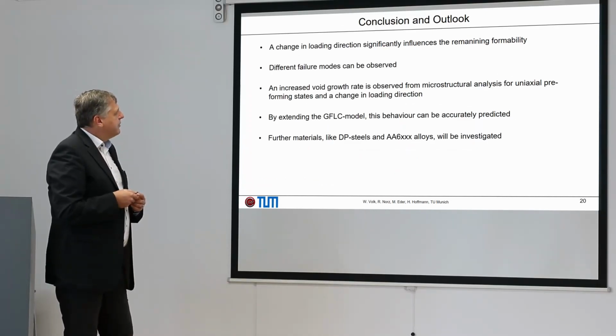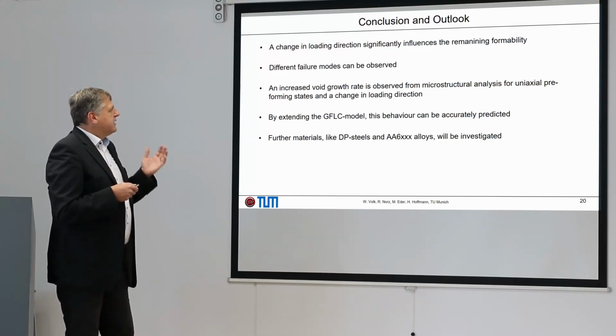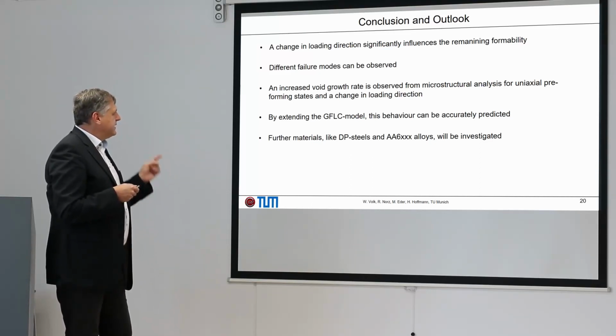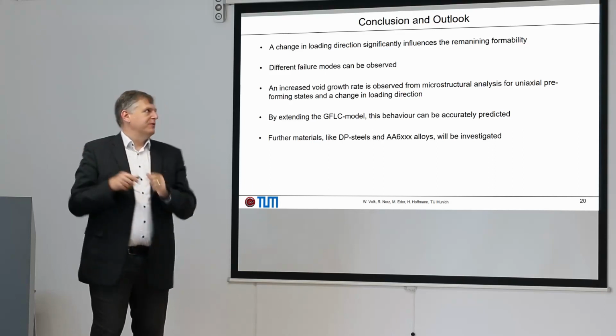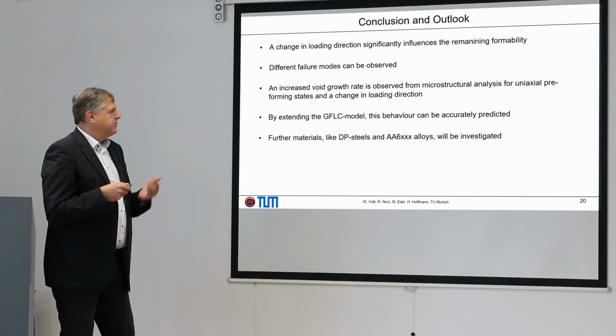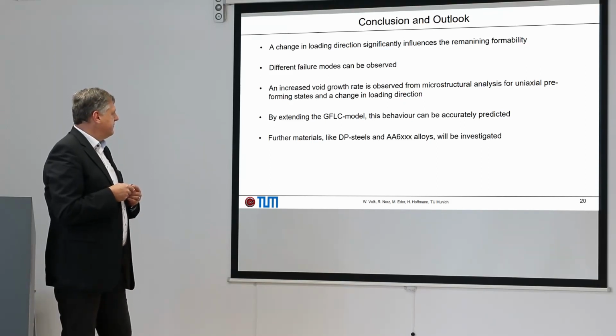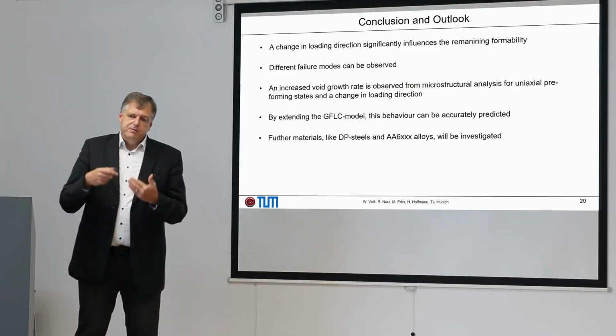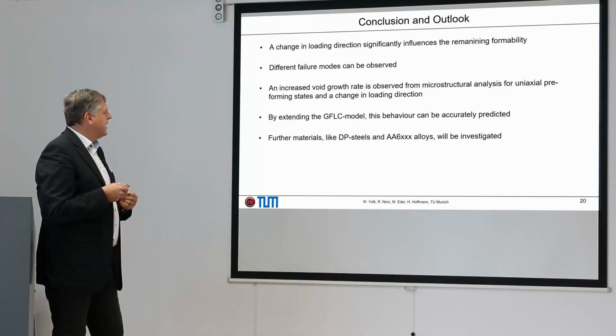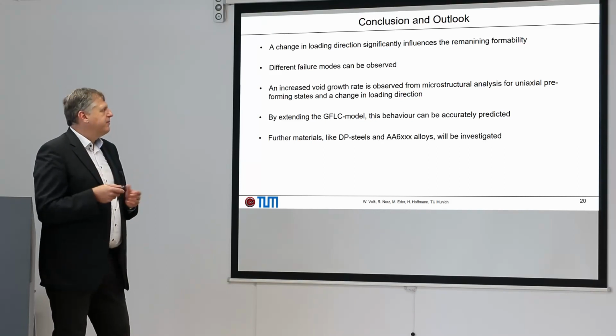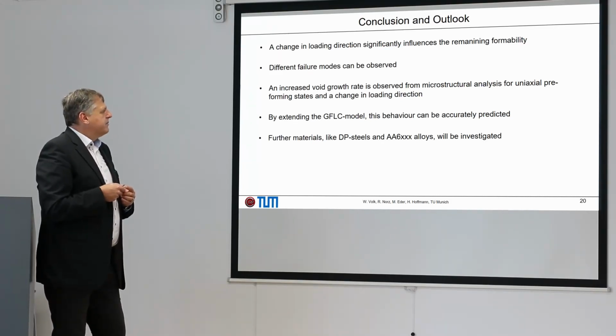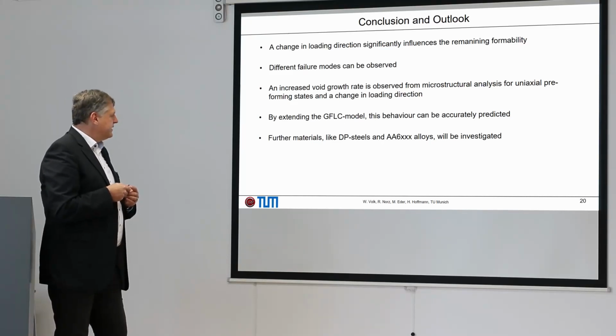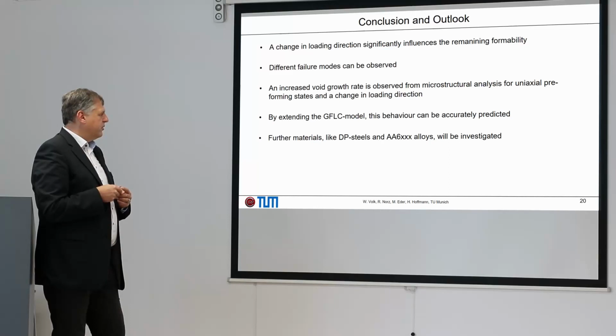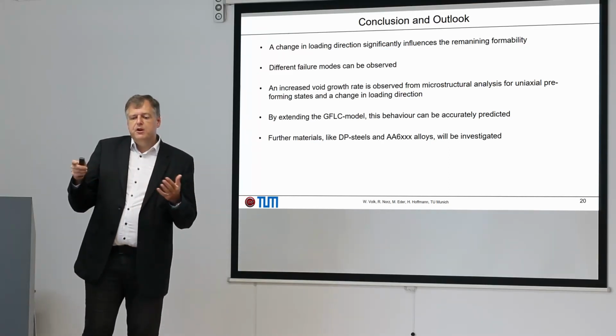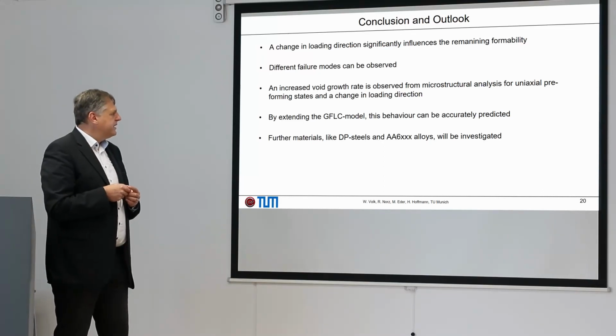So let's conclude our presentation. So I want to summarize again that the change in loading direction significantly influences the remaining formability, change in loading with respect to rolling direction. So also, what was really surprising, that different failure modes can be observed. And also when we have a deeper look inside the material, that a surprising void growth, start of microvoids and void growth based on the microstructural analysis is the reason for that we have these different failure modes. Within the framework of a phenomenological model, it's possible to predict this effect.